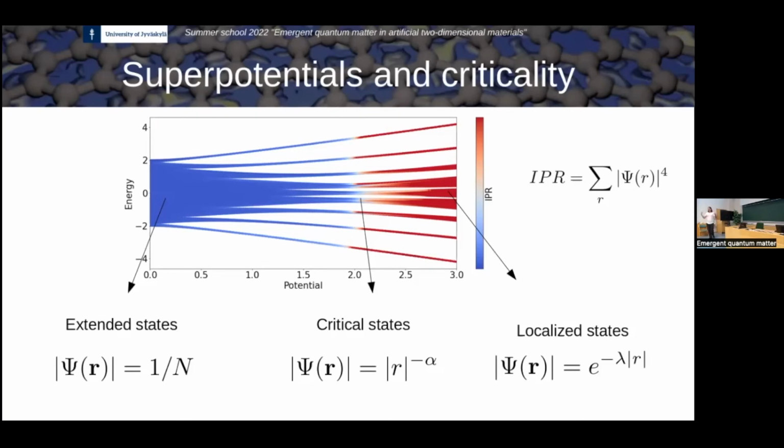And if you can define a unit cell, you can define Bloch waves, and Bloch waves are delocalized. So if it happens that your wave vector is commensurate, you would say that your states are truly delocalized all the time. But what is important is that even in that case, you are going to see a very strong transition between states that are delocalized in your Moiré unit cell to states that are very localized in the Moiré unit cell, even if you have a certain periodicity.